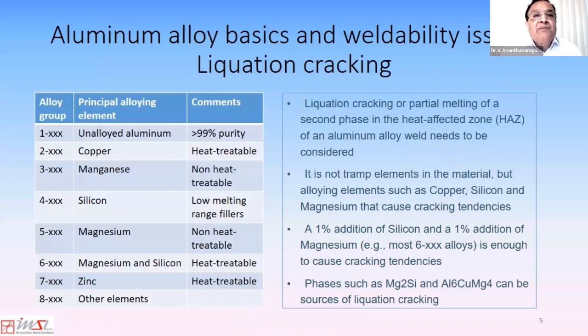And another problem with aluminum alloys is liquation cracking, which is the partial melting of a second phase in the heat affected zone of the alloy. And it's not tramp elements in the material that makes this cracking happen, but alloying elements such as copper, silicon, and magnesium that are added in the alloy. And I will show you some micrographs later that show second phases of this alloy in the heat affected zone that melt during welding and cause this liquation cracking. Phases such as Mg2Si and Al6CuMg4 and other phases are the sources of such liquation cracking.